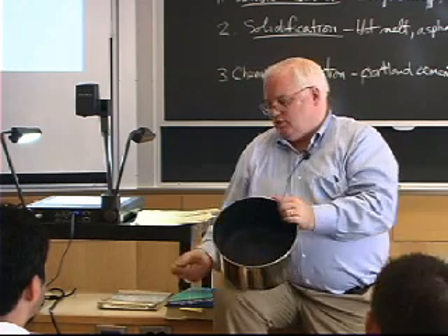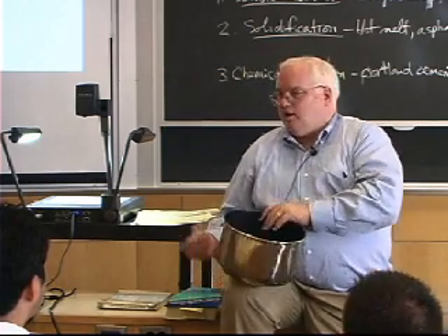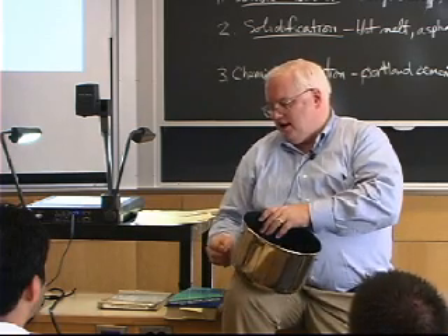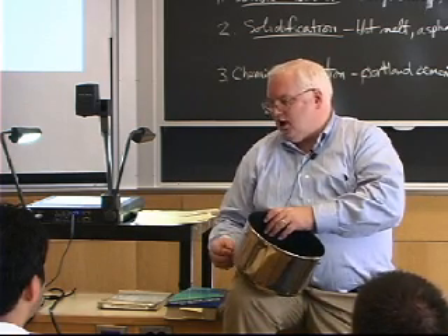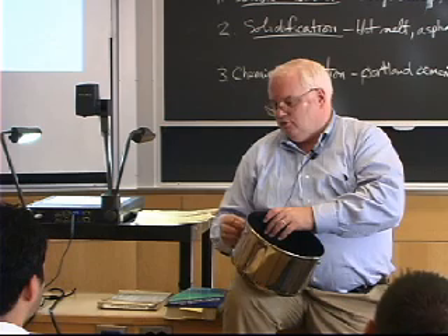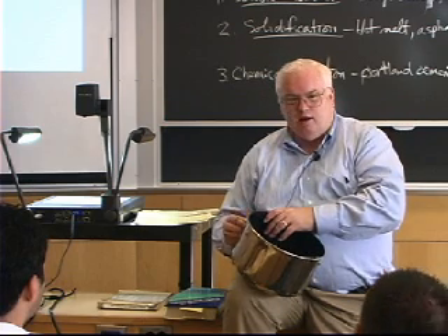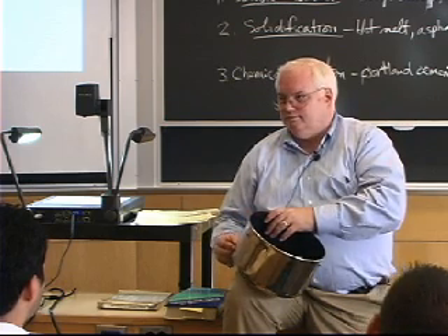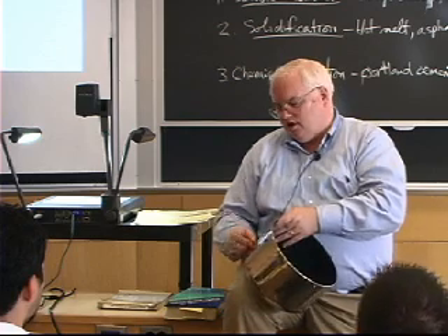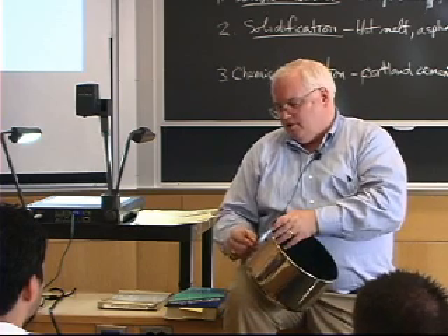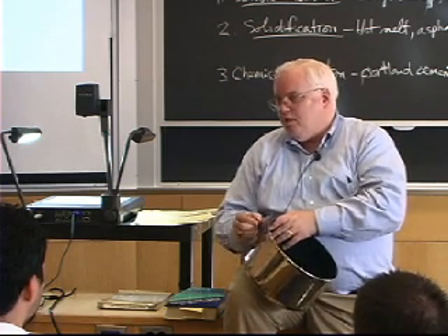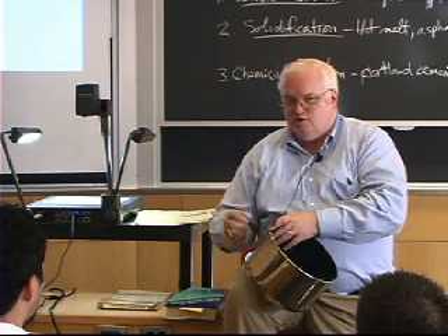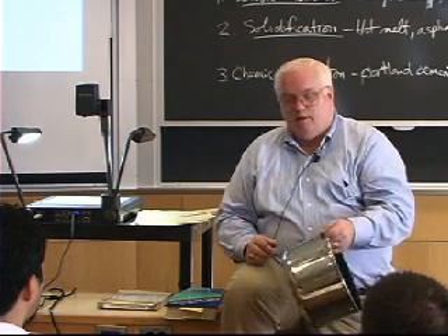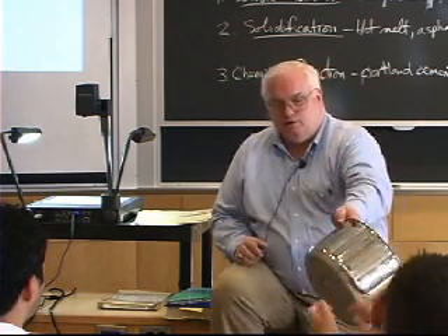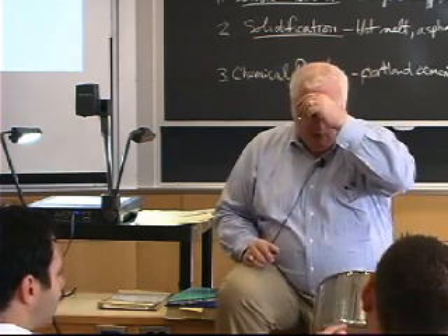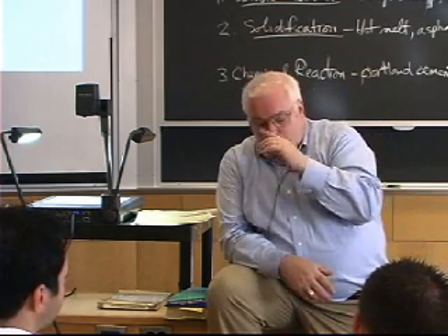However, what I did, they were sitting down in my office around the table. I went and I got a magnet, and I said, yeah, it's stainless steel. It's only slightly magnetic down here. But if you get up here, it's really magnetic. The reason it's got tabs on here, we ended up having a student go through and measure the liftoff force. We have a little gauge down there that they actually use to measure the amount of ferrite in weld.